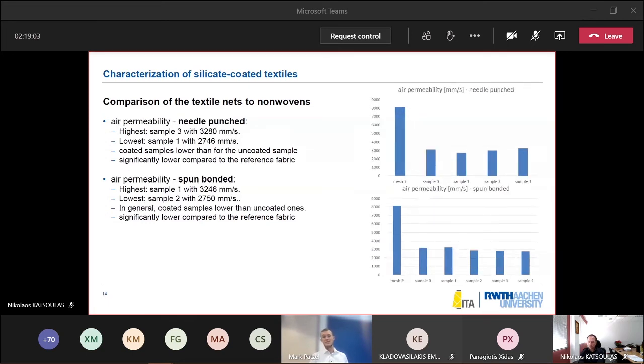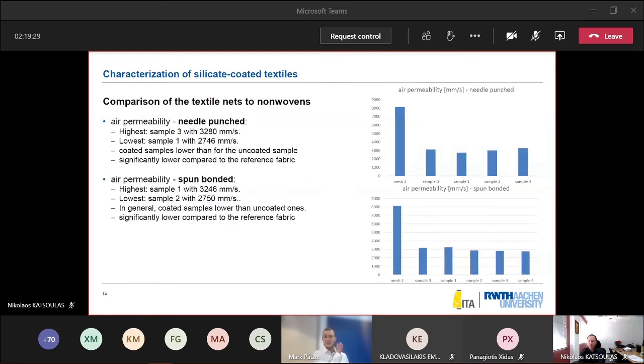Then about the air permeability, the highest air permeability for needle punched is sample 3. I will not tell you all the numbers, I think it's a little bit too much, but you can see the numbers there. And for spun bonded, it's sample 1. The lowest air permeability for needle punched is sample 1, and as you can see also in the graph, the lowest for spun bonded is sample 2. For needle punched, the coated samples have a lower air permeability than the uncoated sample and significantly lower compared to the reference fabric. And for spun bonded, it's kind of the same.